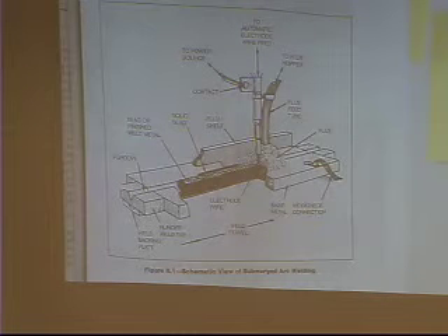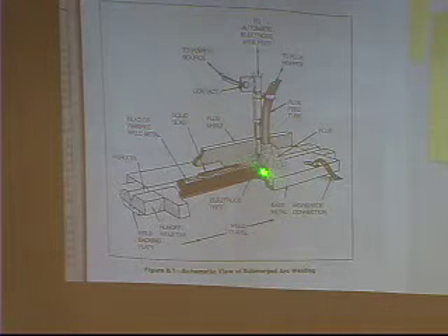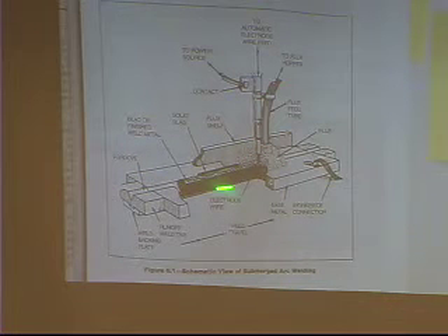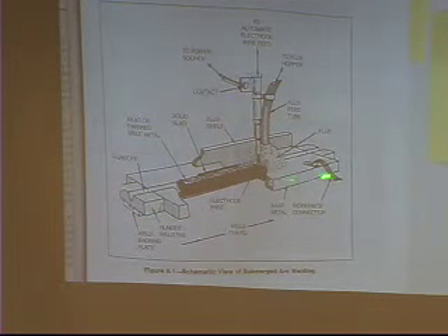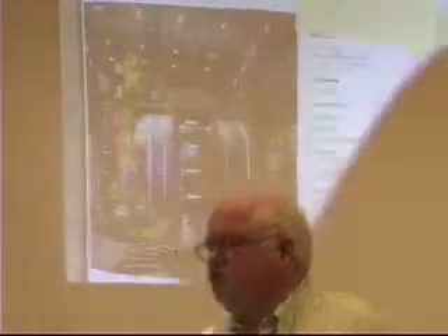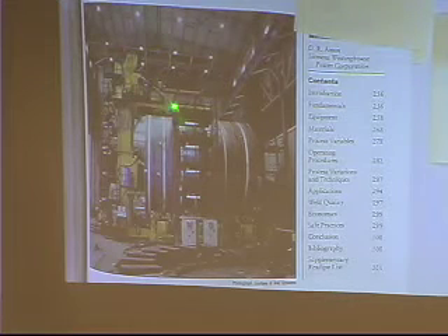You can walk by this, nothing on you. You'll see every now and then a few little bubbles of gas pop through, and you'll hear the thing kind of sputtering a little bit. You can tell that an arc's going on, but you can have anywhere from 500 to 2,000 amp arc and put in huge deposits. But the problem is it only works in the horizontal position, which is why they can show you this picture and you can get very high productivity welding, but only one weld at a time at the 12 o'clock position. They rotate the whole cylinder.